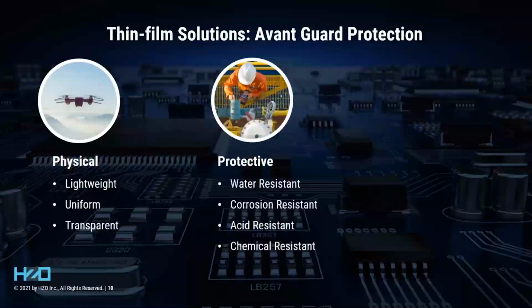Thin films are protective. So for a given unit thickness, thin film solutions give superior protection with less coating. They are broadly chemical and water resistant. They allow less water to move through them than traditional coatings, meaning they're less porous to the migration of water molecules. Parylene has a strong combination of flexibility, chemical, and moisture resistance. And plasma and ALD films can be tailored to a number of characteristics, particularly in regards to their gas permeability or surface properties. So you change precursor chemistry, you change the energy of the deposition, and you end up with a different material that meets your goals.